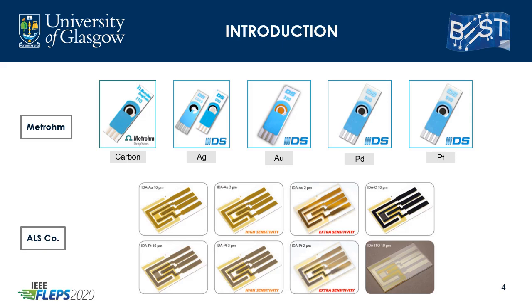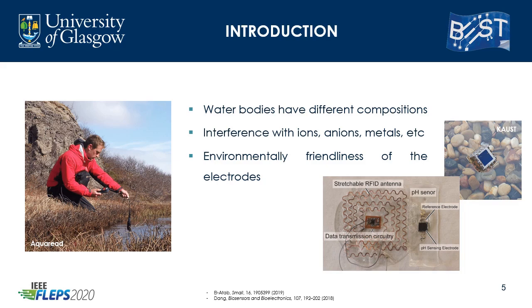However, depending on the medium that they're going to be used in and what is the desired application, different challenges arise. One of the possible applications for printed electrodes is routine environmental analysis, for example, in heavy metal, inorganic nitrogen, and pesticide detection. The choice of material for the conductive path is essential for a reliable ion-electron transfer, and as mentioned before, it is of great importance for a successful electrochemical analysis. Water bodies are a complex mixture of different salts and ions, and the right electrode material can minimize cross-interference. Even when used only as a conductive track, the material of choice might interfere with the sensor response if not well insulated. When dealing with water bodies, we should also consider the environmental friendliness of the electrodes. Materials that are toxic to aquatic life or human consumption should be avoided whenever possible.